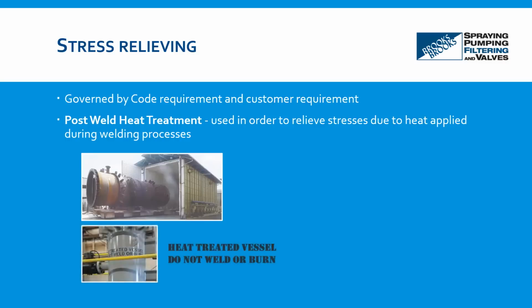And you can also see here where the vessel is stencil painted with the message, "Heat-treated vessel, do not weld or burn." And this is important because if you do happen to weld or burn the vessel, that vessel has to be sent back for post-weld heat treatment and perhaps other testing is necessary. Otherwise, that vessel is no longer to code.